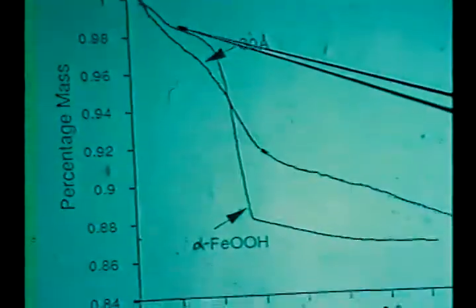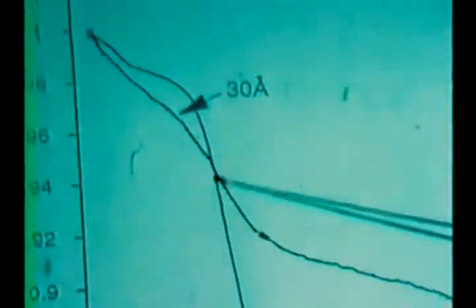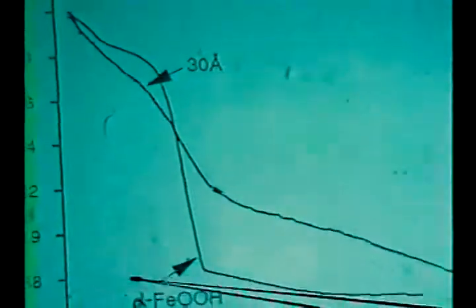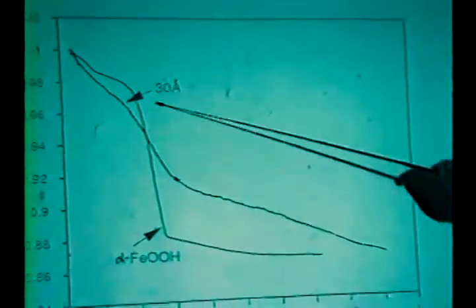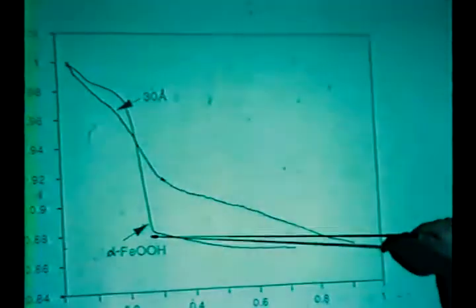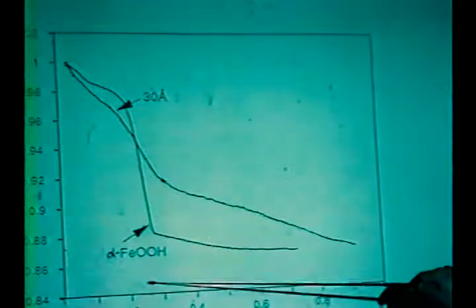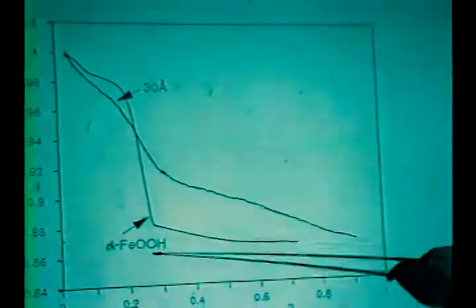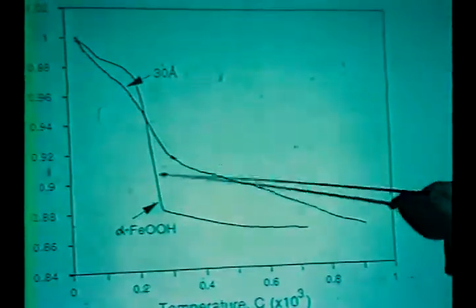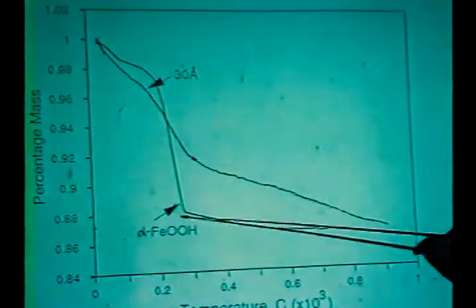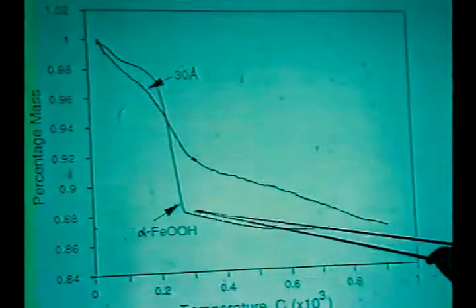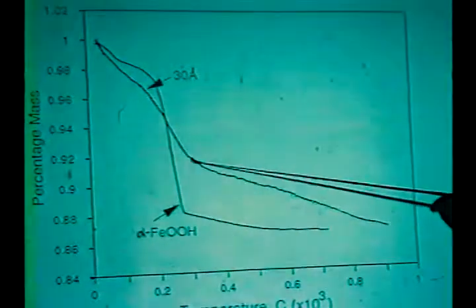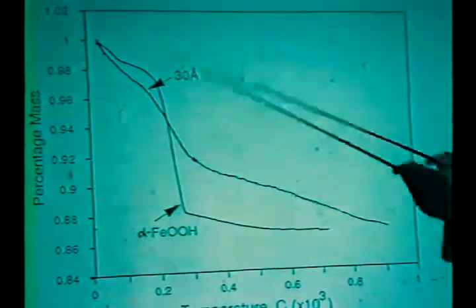Now, if I compare the TGA curve of the ferrihydrite to alpha FeOOH, you will see there's a sharp transition at around 250 degrees for alpha FeOOH. It means around 250 degrees, all the alpha FeOOH converts to hematite by losing weight of water. But you don't see a clear-cut phase transition for the ferrihydrite. So why?